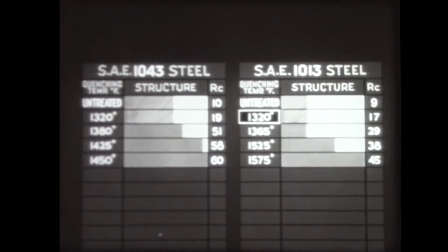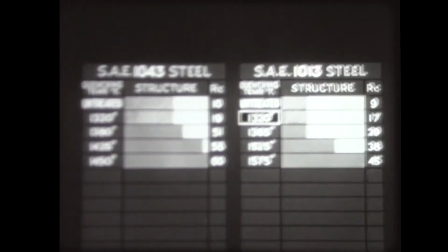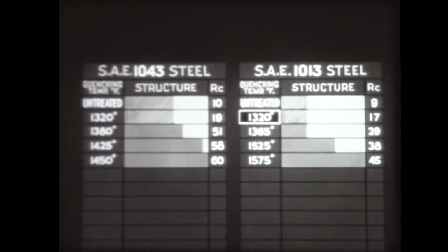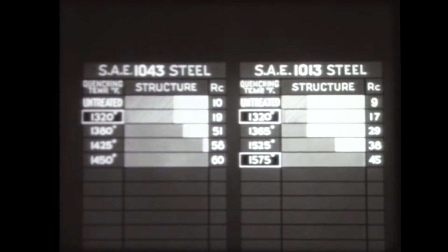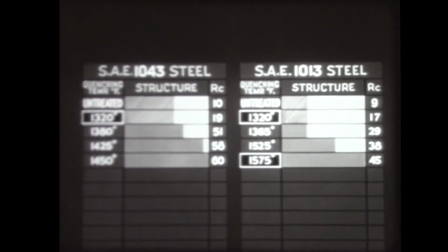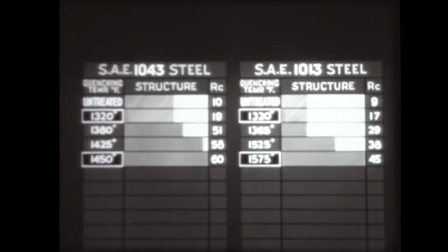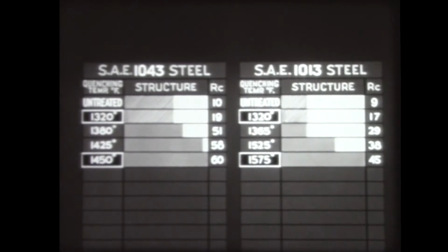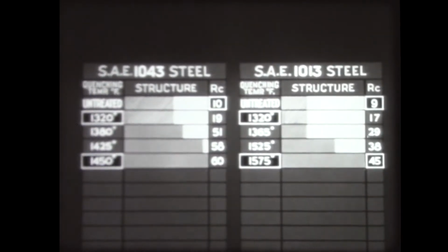Here is the point of initial hardening in the 1013 steel. 1320 degrees Fahrenheit is its lower critical temperature, just as it was for the 1043 steel. Here is the point of maximum hardness for the 1013 steel. 1575 degrees is its upper critical temperature. This is considerably higher than the upper critical temperature of the 1043 steel, which was fully hardened at 1450 degrees. Where the original hardness of the two steels was very close, 9 for the one and 10 for the other, the maximum hardness obtainable in the lower carbon steel, 45, is considerably less than that of the higher carbon steel, 60.